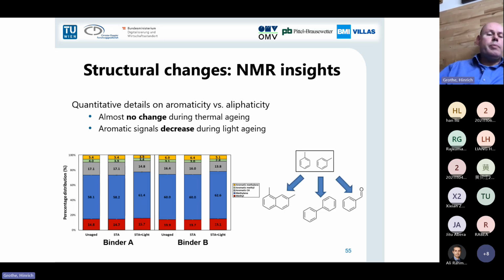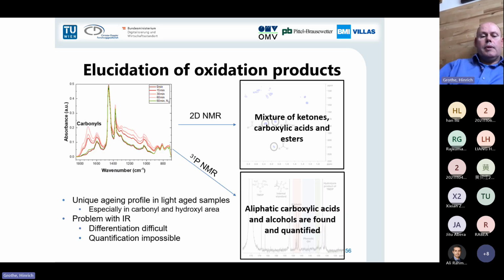And then with NMR spectroscopy, we can even quantify. We can show where changes happen. And what is also interesting to observe is that the aromatic signal decreases during light aging. That's understandable on one hand, but it's also a little bit contradicting what we observe with the infrared. Because with the infrared, we see things a little bit differently, but also here the 4 different fractions were oxidized and spectra were recorded. And as I said, we are correlating then with NMR spectroscopy, and we see that we produce a mixture of ketones, carboxylic acids and esters. And with the phosphorus NMR spectroscopy, we can also see the carboxylic acids, alcohols, and we can quantify.